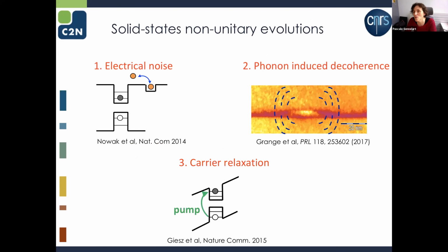There are many reasons why it shouldn't be possible with our system. If there are any kind of traps not too far from the quantum dot, I can have this kind of fluctuation of the electric field around the quantum dot, and this will lead to charge noise, which will lead to the generation of always different photons. There is also the possibility to have coupling with phonons, the vibration of the crystal. This would be very bad. And also, it's very important to see how I create the carriers in the quantum dot, because if I don't do it the right way, there may be some non-controlled process before spontaneous emission.